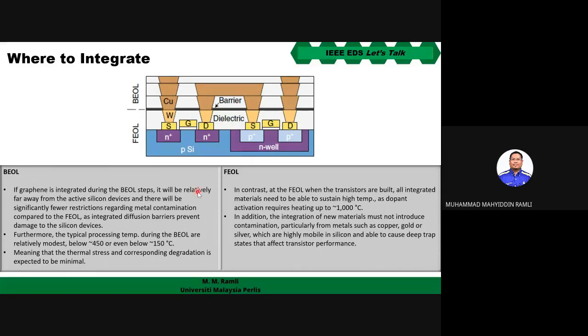Okay? But if we try to integrate into the back-end process, it will be easier compared with the front-end process, even though it won't impact that much in terms of the device performance. Why? Because typically for the back-end process, the process temperature that we use is only around 450 degrees C or even below 150 degrees C. But if we try to integrate the graphene in the front-end process, in contrast, it needs to sustain a high temperature for dopant activation, especially for our implantation or well creation, it will need more or less 1000 degrees C.